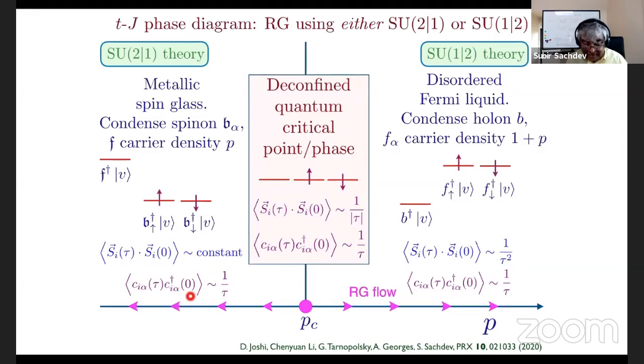It's still a Fermi liquid because these guys are moving around as fermions. There's some density of them. But the density of these is the density of holes, which is density P. So there's a lower density of these fermions moving around. So there's some kind of metallic spin glass with low carrier density. So that means there's a phase here. This is the proposed pseudogap phase of this model, which has spin glass order and also has a low carrier density. Whereas here it's a disordered Fermi liquid with no broken symmetry and a high carrier density.